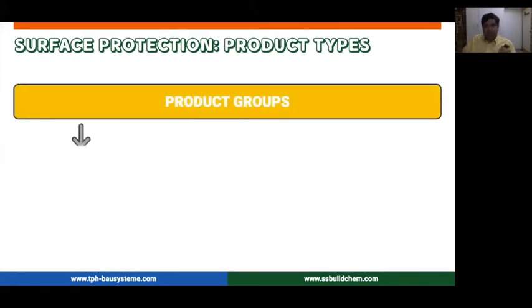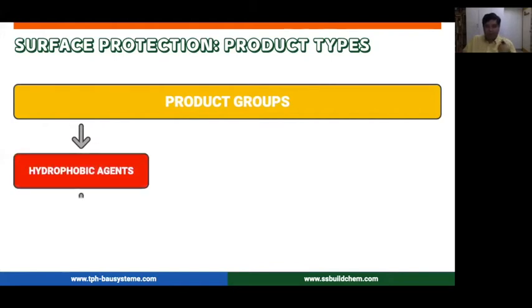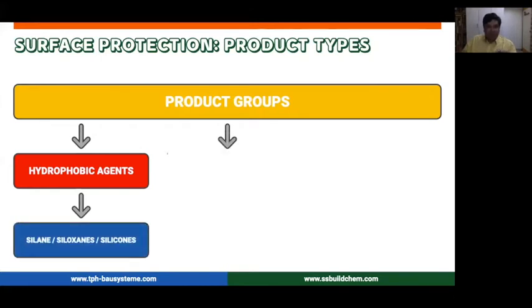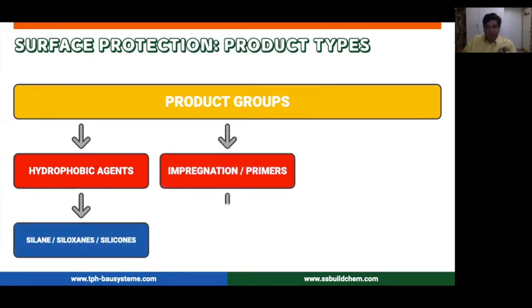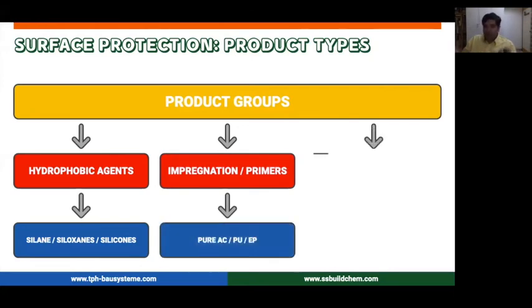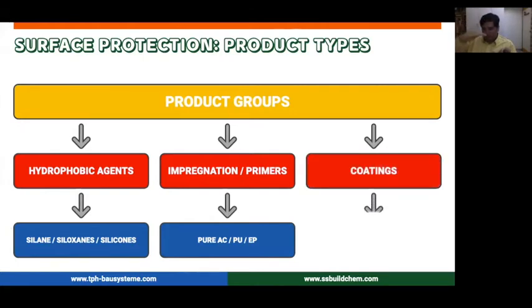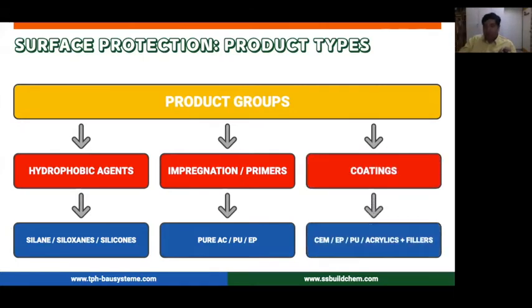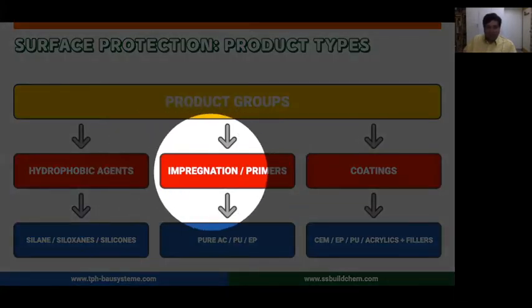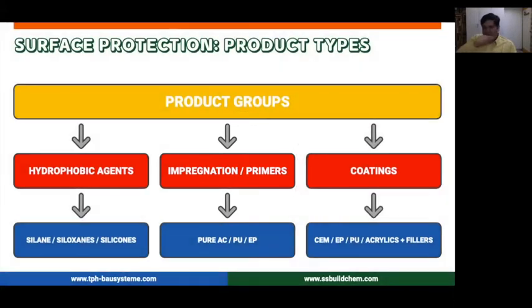Now, surface protection systems, we can break it into different product groups. There are three basic product groups based on the EN criteria. The first one is your hydrophobic agents, and these are based on simple silane, siloxane, silicone based polymers. So you apply them, and they go about 4, 5, 6 mm into your concrete substrate and hydrophobize it. So that's why they're mostly called hydrophobic agents. Then you have your impregnation and primers, which leave a very thin film. They impregnate into your concrete but leave a very thin film on the substrate. So they also act mostly as what we call primers.